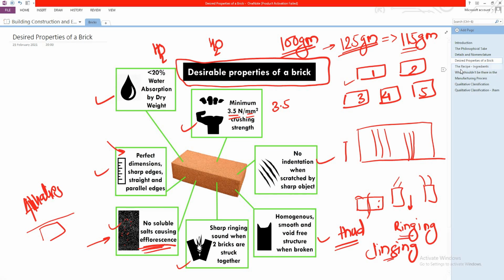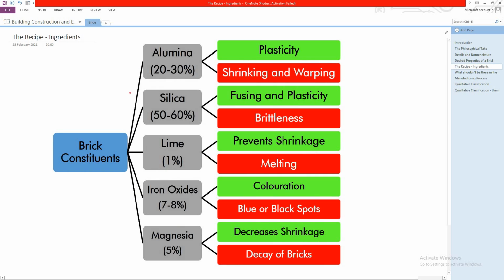Then let's see what are the specific ingredients that we are going to use for making a brick. See, here a chart has been provided and brick constituents have been split into the respective percentage ranges, provided with minimum and maximum. Now here the green indicates, the first example is alumina. When alumina is present as a brick constituent between 20 to 30%, precisely more than 20 and less than 30, then it imparts a useful property, plasticity. And in case the percentage goes below 20 or goes above 30, then this red coloration phenomenon takes place, which is shrinking and warping.